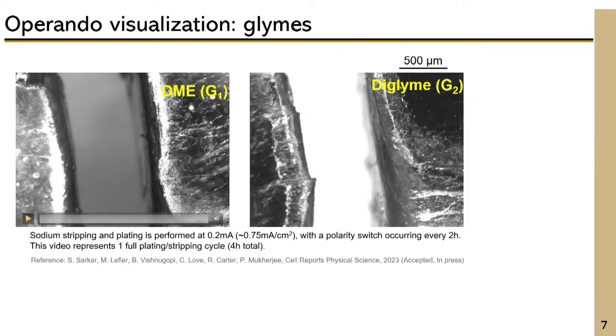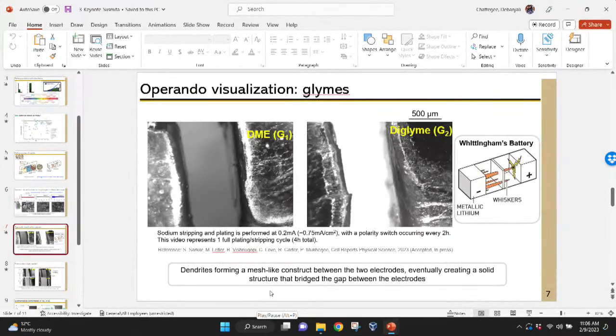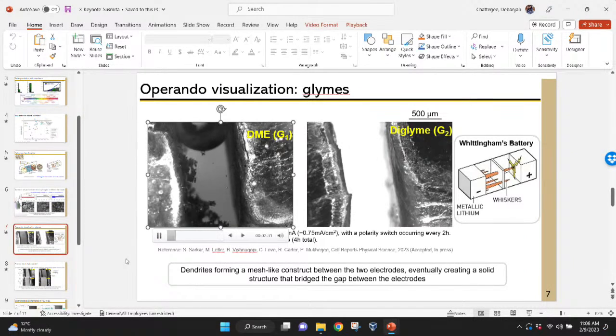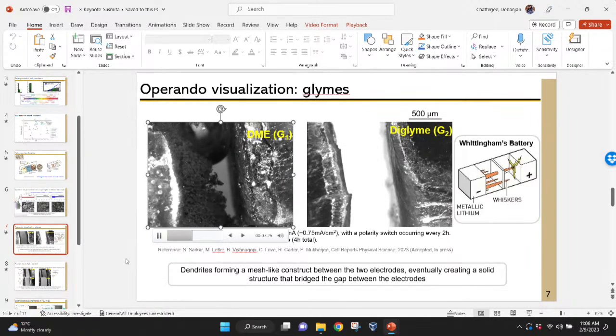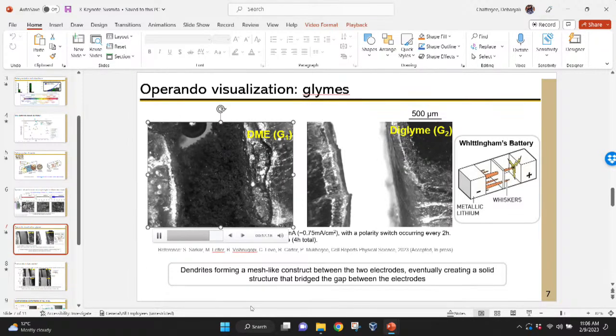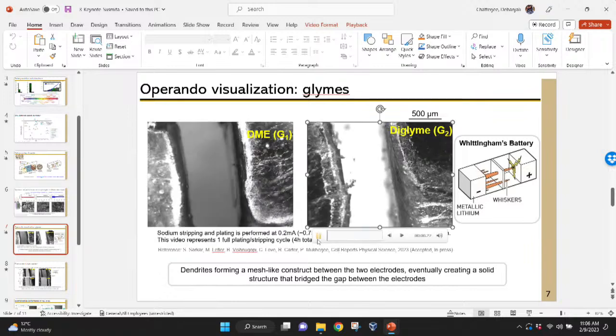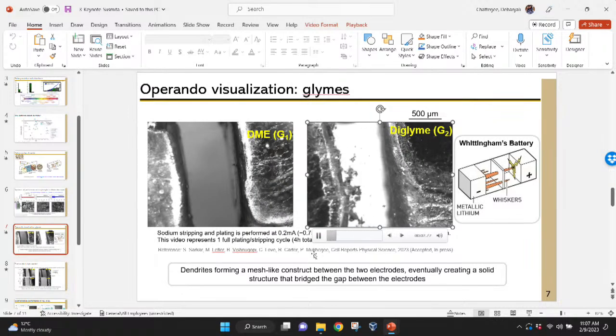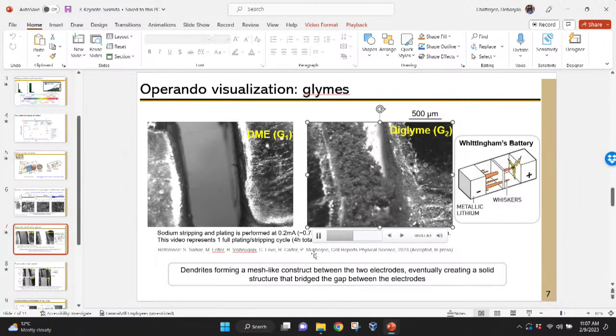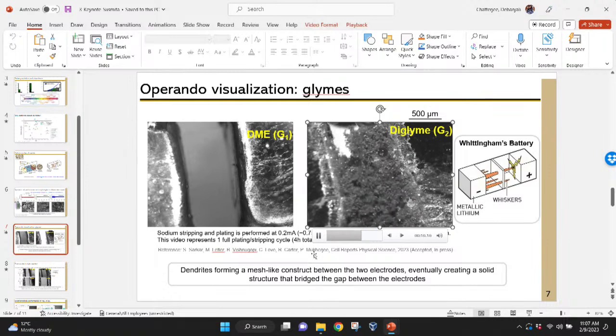We already know the tetraglyme, the last case, is not good. So we selected these first two cases to show that under operating conditions, it's actually showing huge dendrites, creating a mesh structure between the two sodium electrodes, which is causing a short circuit. Now in the second electrolyte, the diglyme case has a similar thing. So what we thought was a good electrolyte isn't actually showing this kind of dendritic growth when seen under the microscope in operando.